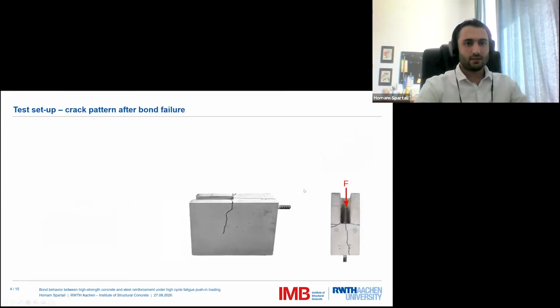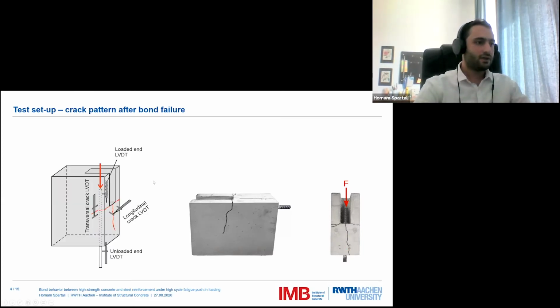The specimen was subjected to the loading in this vertical orientation. And this was the most prevailing failure mode, with two transversal cracks and one longitudinal crack along the bond zone. Regarding measurements, we used four LVDTs, two to measure the slip at the loaded end and the unloaded end, and two to measure the width of the longitudinal and transversal cracks.